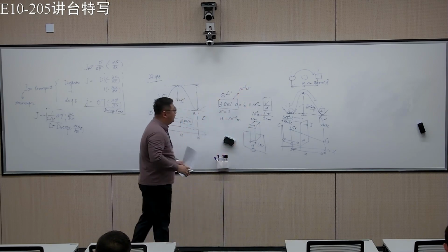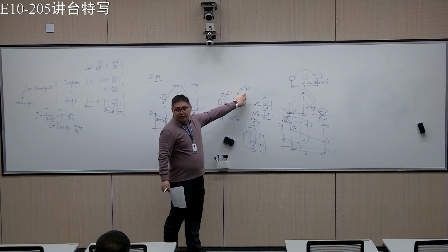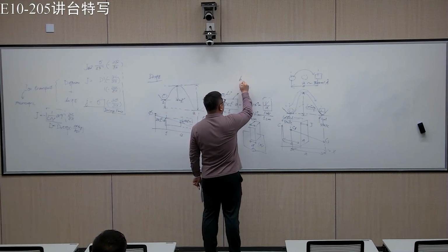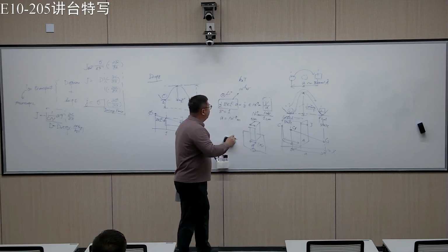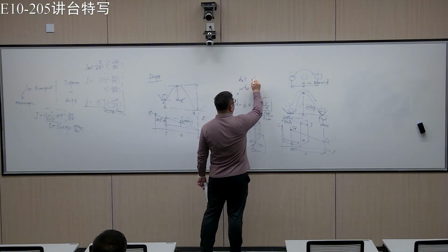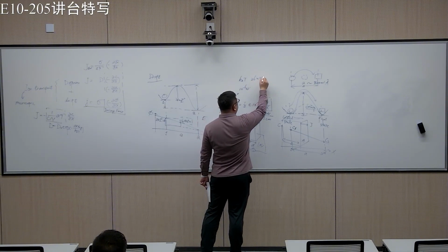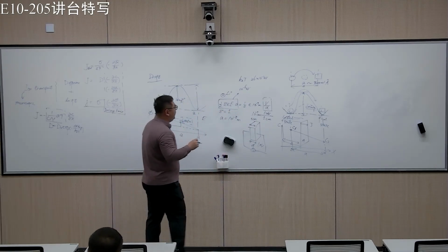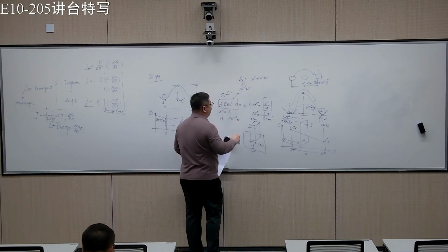So is this a large or small value? It's very small, right? Because we know that kBT is 26 meV, which is much larger than this value.